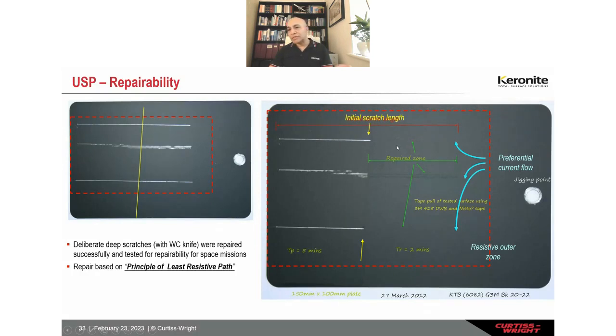On the right, what you can see is a forced healing, I call it, in the electrolytic bath. You cannot see even a seam here. It's almost seamless. On this one, you can see a little bit like scar tissue, like on human skin. You can see that. But when we measure the properties, they are identical to the original. The bond was extremely good. The adhesion was good. The reflectance was good, and the cross-section also looked very good.